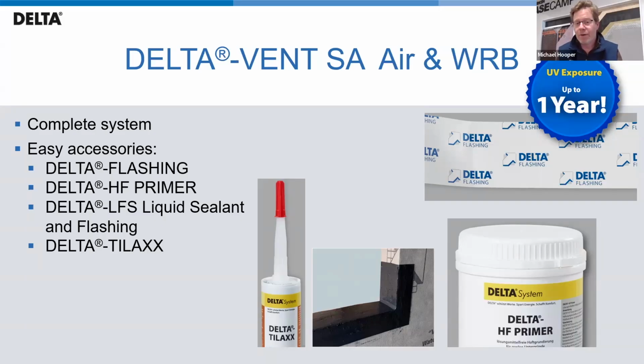In this case, it's a moisture cure silicone. You can't use an acid base. So always try to use the same manufacturer. And in this case, because it is a fluid, you can terminate it. There's no big deal with a reverse lap with this. The only downside to silicone is the only thing that really sticks to silicone is more silicone. So keep that in mind if you have to put something over top of it. If you need to lap a sheet membrane over top, my advice is to apply more silicone and then set the sheet membrane in the wet silicone, let the wet silicone cure through that membrane. Otherwise, it is not going to stick.